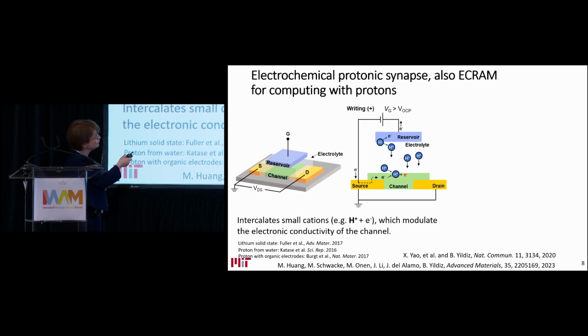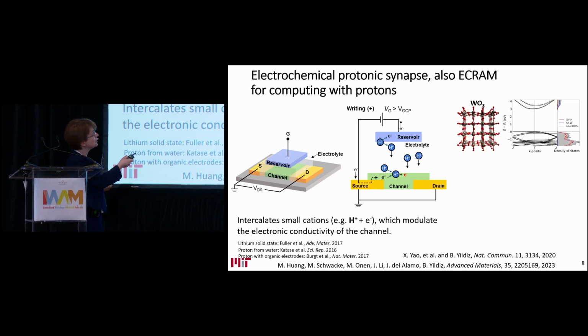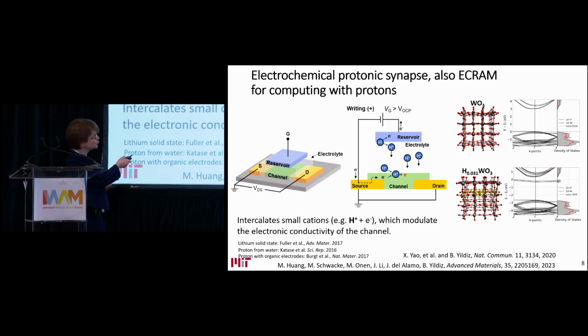So in such a device, then we store proton in the form of hydrogen in a solid reservoir. And as we apply positive potential, we oxidize hydrogen to proton that migrates through the electrolyte, and the electrons take the outer circuit, and they arrive at the channel. And if you have chosen the channel material appropriately, the electrons can be donated to increase the electronic conductivity of this channel material. For example, if we look at tungsten oxide, which is a semiconductor with about 2.8 eV bandgap, the electrons brought together with the protons are donated into in-gap states associated with tungsten. They form polaronic carriers and increase conductivity. So every proton brings an electron that contributes to polaronic conductivity, as an example.